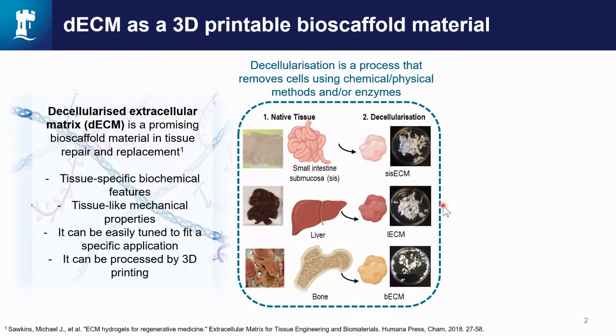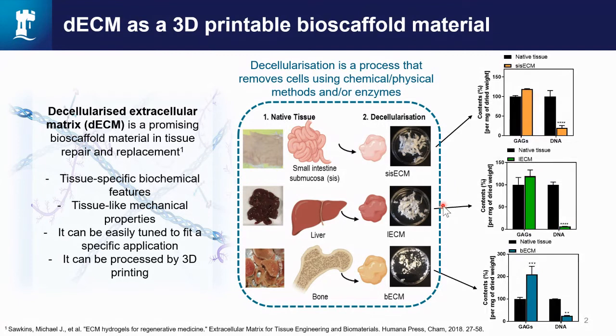In our case, we worked with three different tissues: small intestine submucosa, liver and bone. And we decellularized these three different tissues using chemical, biochemical and physical methods. Once we decellularized them, we characterized the glycosaminoglycan and DNA content. We've seen that our GAG content was quite high, which is good because it means that the structural proteins are still present in our matrix. Also, the DNA content is quite low, which is also good because it means that we have effectively removed the cells from our tissues.